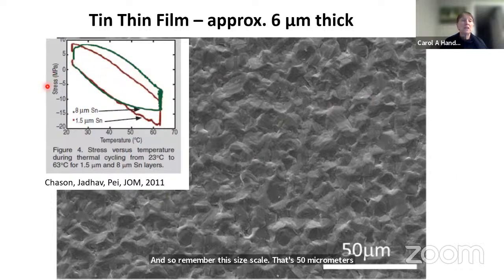So here is a plot, this is from the work of Chason et al. You take the film. Now it's on a silicon substrate. So the thermal expansion of silicon is different from tin. It's different by an order of magnitude. So we thermally cycle this material. We have a tin thin film with a thermal expansion coefficient of 23 times 10 to the minus 6 per degree centigrade, and it's on a silicon substrate, which is about an order of magnitude different. When you heat it up, it puts the tin film under compressive stress.